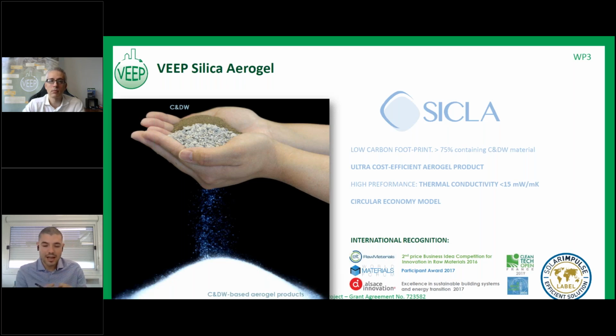We are extracting the silica and we are producing the aerogel directly with that. So we are obtaining an aerogel product, what we call SICLA, with a very low carbon footprint because we are using more than 75% on weight of construction and demolition waste. We are able to provide a very efficient, low cost production of the aerogel, and we are obtaining an aerogel with the same quality as any commercial aerogel with very good thermal properties and providing a very nice circular economy model. This system has been recognized by different international awards, where we should highlight the fact that this technology has been labeled like an efficient solution within the Solar Impulse Foundation.